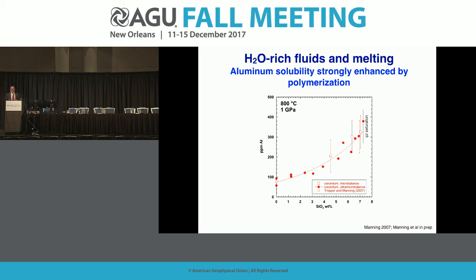Well, anybody who works on silicate melts knows that there's another important network forming cation that's not silicon, it's aluminum. And so what happens if we add aluminum to this system? Well, here's a set of experiments showing the solubility of corundum in pure water over on the left here. And as we add silica to the solution, you can see that the experiments shown in the red symbols indicate that the solubility of Al2O3 increases. This increases pretty profoundly up to very high values here.